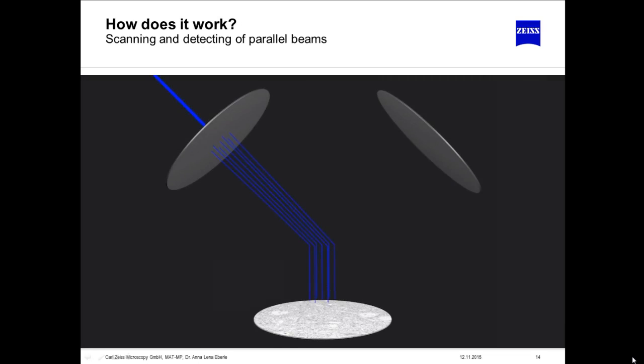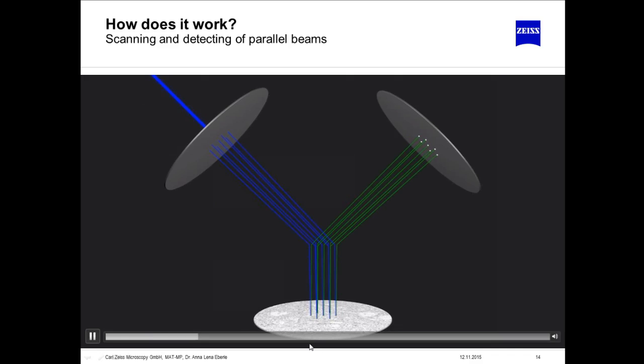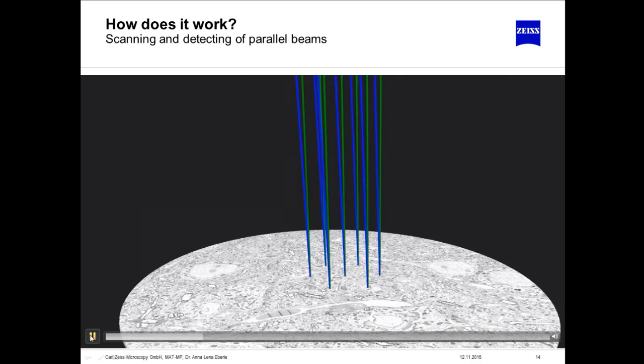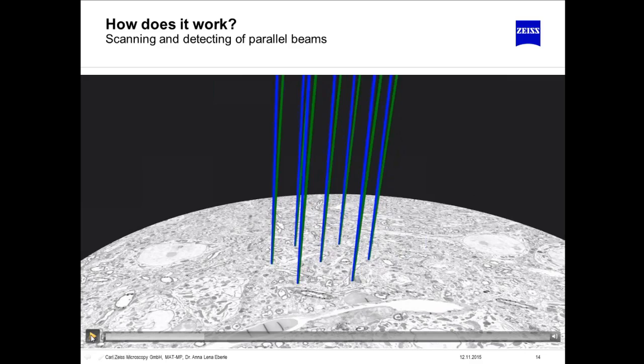Now, a single electron source produces a single electron beam, which goes through a multi-hole aperture, and therefore ends up as an array of multiple beams. These are shown in blue. And they are bent with an electromagnetic beam splitter towards the sample surface and focused onto the surface, scanned globally. The secondary electrons, shown in green, that are generated on the sample surface are collected and separated from the other electrons by the beam splitter.